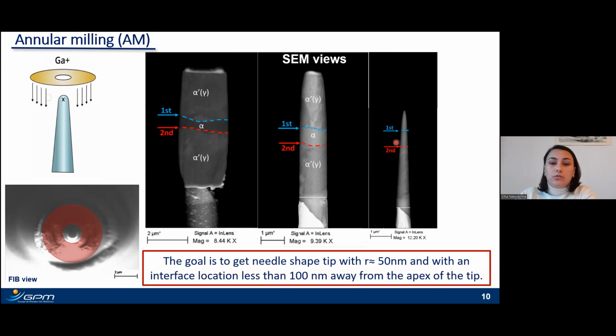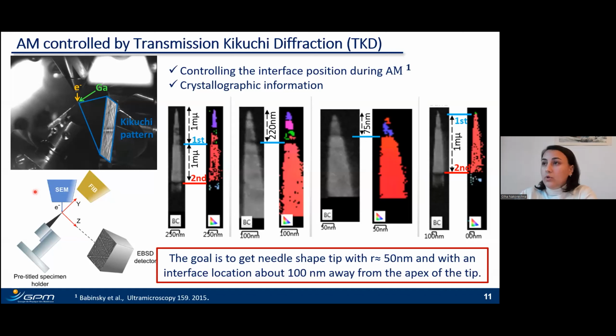Therefore, to control the interface position, we use the TKD technique, that is a transmission version of EBSD. As you can see on the slide, after several steps of annular milling controlled by TKD, we can localize the first interface at the desired distance. And it's ready to be analyzed by APT, but we will not be able to analyze the second interface in the same APT run, because as you can see here, it is approximately 1 micrometer away from the first one.